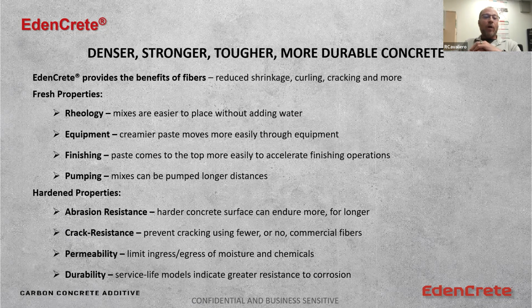So when we look at permeability, EdenCrete's integral. It's added during the batching process at the concrete plant. There's a lot of products that are topical. They're placed on top and finished into the surface, or during finishing or after finishing. And they help with the concrete, but only in a short top section, maybe 1/8 or 1/16 of an inch. EdenCrete's integral. And so we flood the cement paste matrix with all these nanoparticles, and we help to slow the ingress and the egress of moisture in and out of concrete.